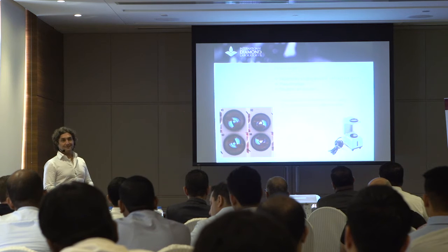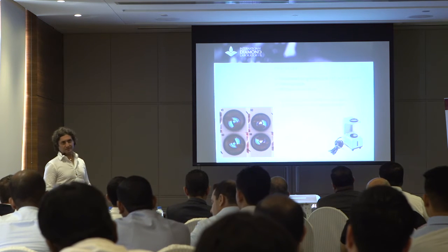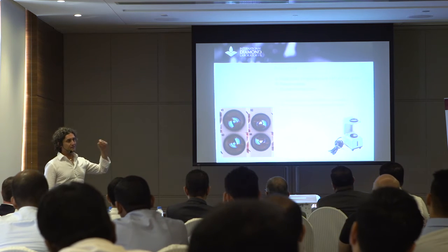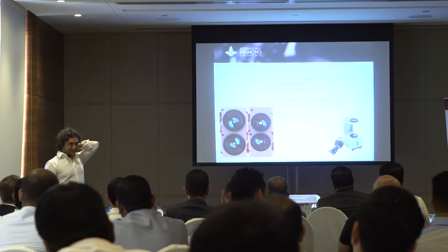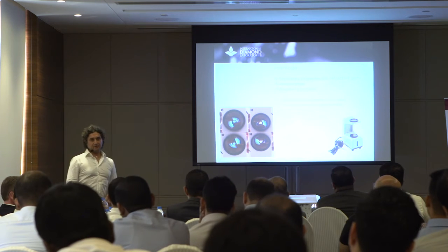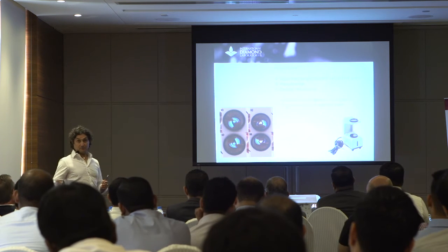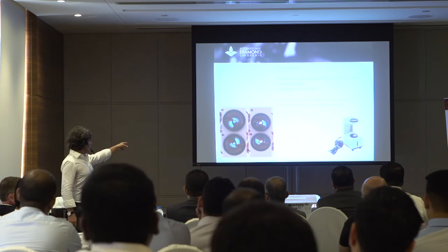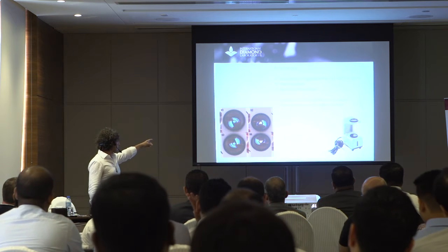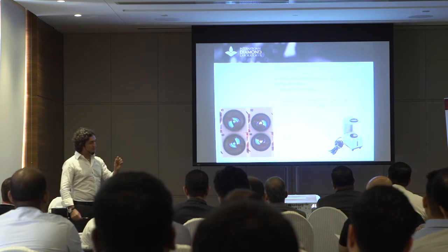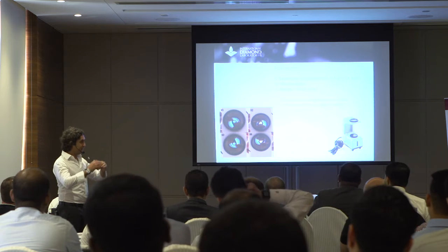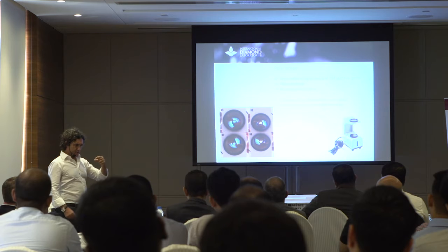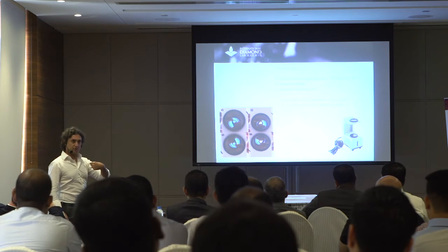It's a very important test because, for instance, with red stones, a red spinel, a ruby, or a red garnet, I can easily separate the ruby, because the ruby is double refractive and the spinel is single refractive. So what I will see is light and dark, according to my moving the stone between the filters.